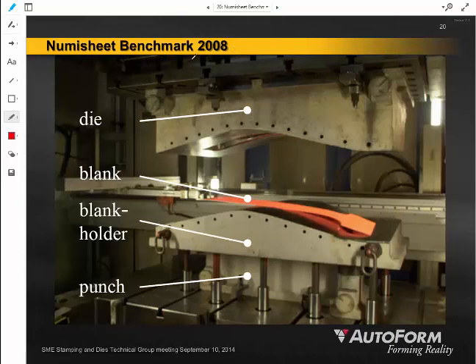So here's an illustration of a part that was produced specifically for a simulation benchmark study by an organization called Numisheet. And you can see here there's that blank. That blank's still red hot, and you'll notice that it's touching at the top of the die, right about midway through that B pillar, and it's also resting a little bit here at the bottom. And as soon as that die starts making contact with the sheet metal, the die is going to start acting like a heat sink for the material, drawing out some of that heat, causing it to cool or quench maybe a little bit earlier than was planned.